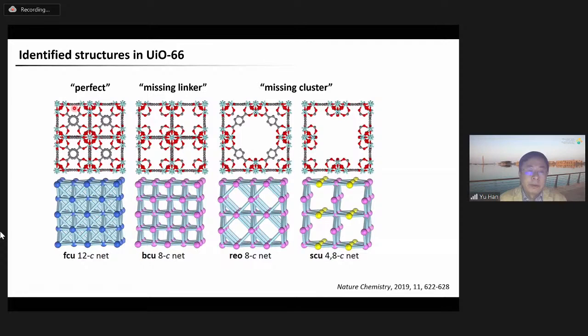This is the perfect structure model. This is the missing linker defect. And we identify another 2 types of missing cluster defect. So totally, we identify 3 defective structures in this sample, and their framework openness increases in this order from the left to the right. The framework becomes more open from the left to the right.